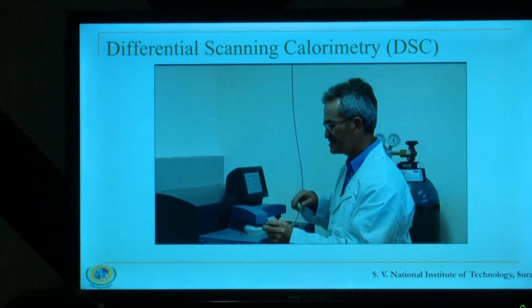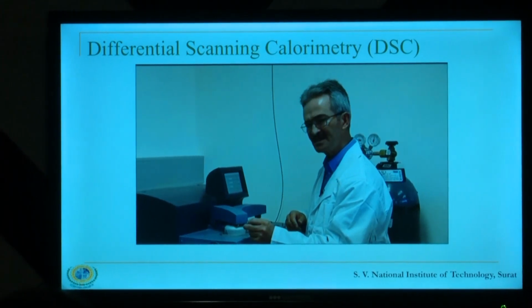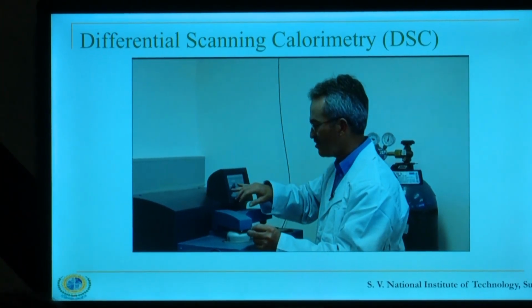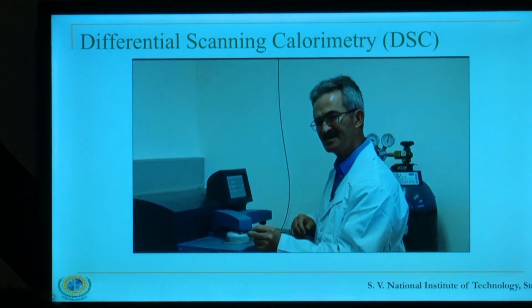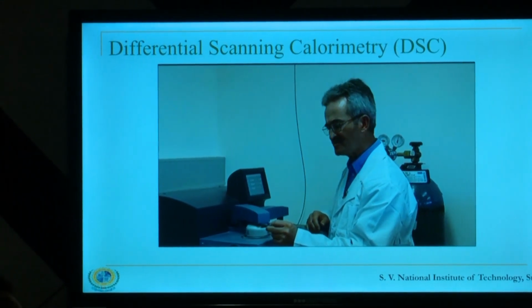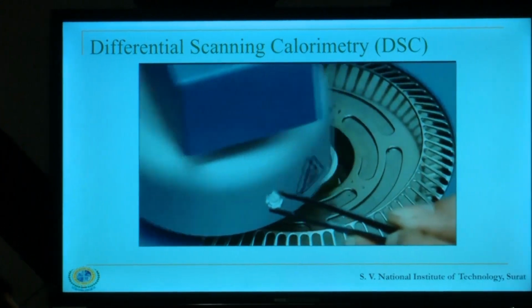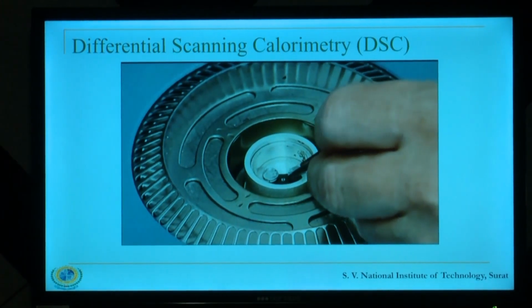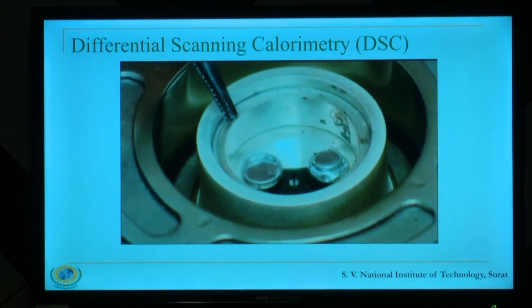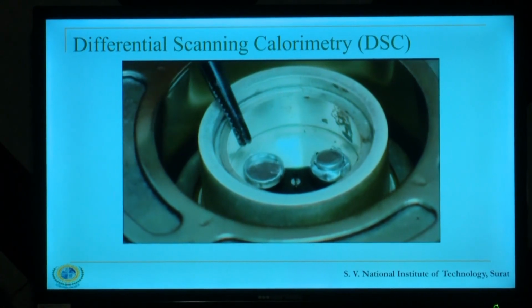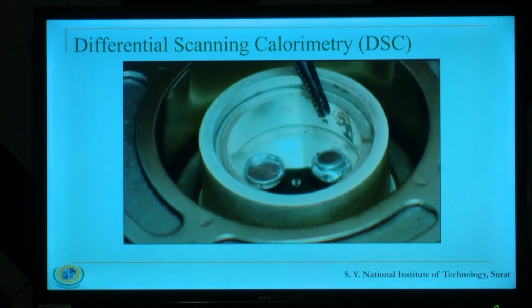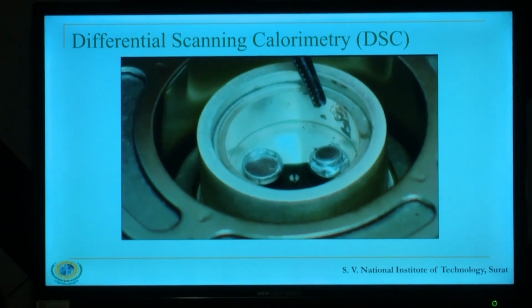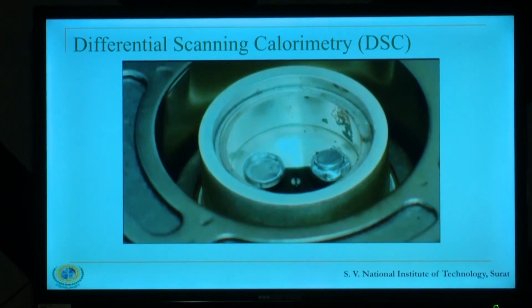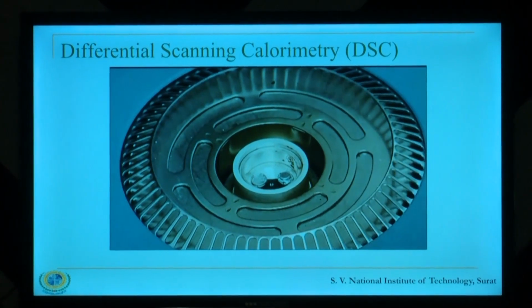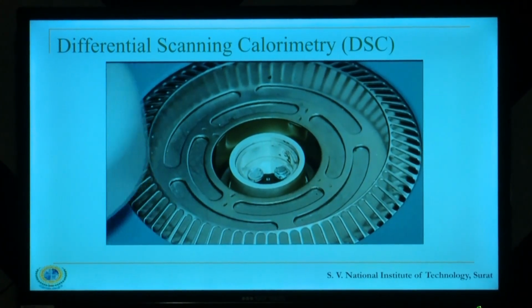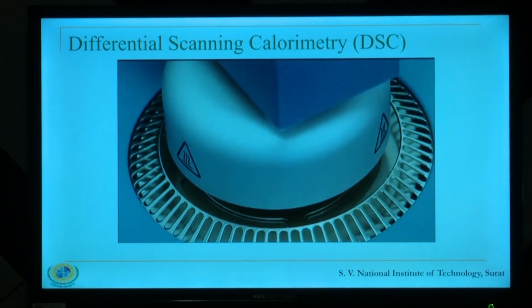Here is the DSC instrument. We bring the sample, sealed inside the aluminum pan. Open the cover of the DSC instrument and get ready to put the sample on the right side. Depending on what sort of study we want to go for, maybe we need to create a nitrogen environment, and in some cases we also allow regular air. Sometimes we need to avoid oxygen. So that choice goes with the type of material we are working on. Then we are ready to start the DSC analysis of the sample.